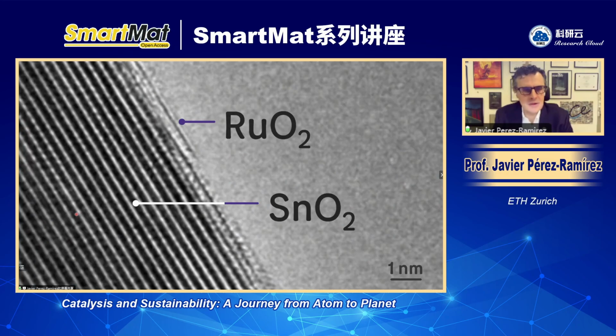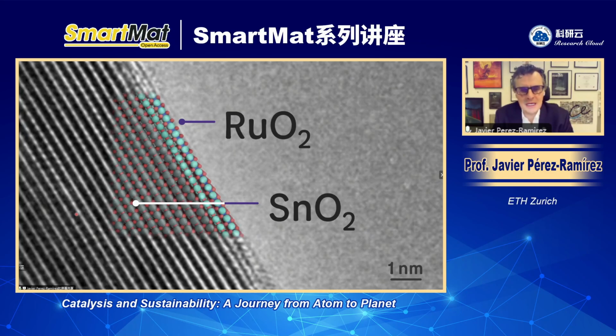Now, seeing is believing, as you know, so this is a high resolution transmission electron micrograph of the catalytic material, where you can see two layers of ruthenium oxide epitaxially grown in a film-like architecture on tin oxide. So this is a catalytic material that was developed rationally in order to achieve circularity regarding the chlorine looping in the production of polyurethanes. That's how catalysis can help.